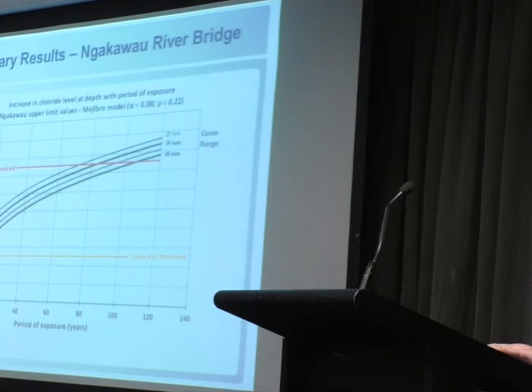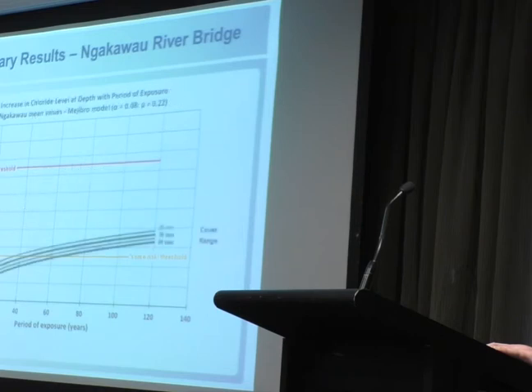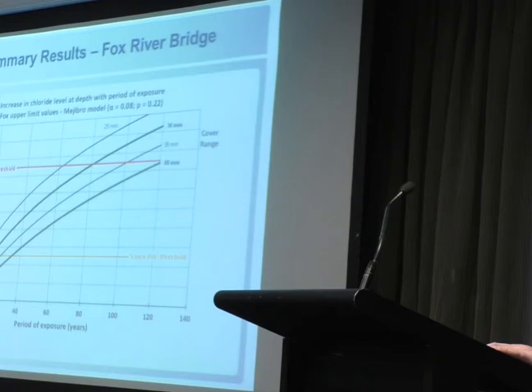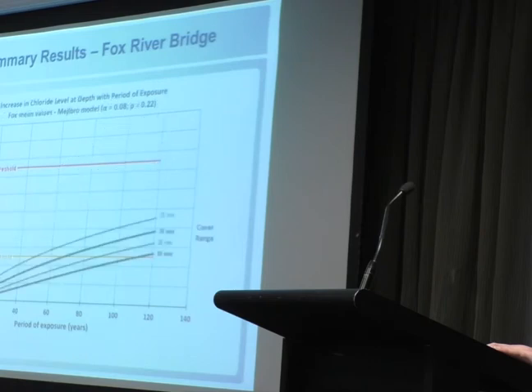Should you be putting cathodic protection on as soon as the 0.05 threshold is breached, even if there's no evidence of reinforcement corrosion, or should you just be monitoring the structure? Is that too non-conservative? And similarly, results for the Ngakawau River Bridge, similar again. Very much dependent on whether you choose to adopt the rise in surface chloride concentration and what reinforcement corrosion you accept. So even though we've collected a lot of data, it's still quite difficult to know what to recommend for these structures, other than that they are potentially at risk and you need to pay attention to them and monitor them regularly and do some of the things that's been suggested, like electrochemical potential surveys.